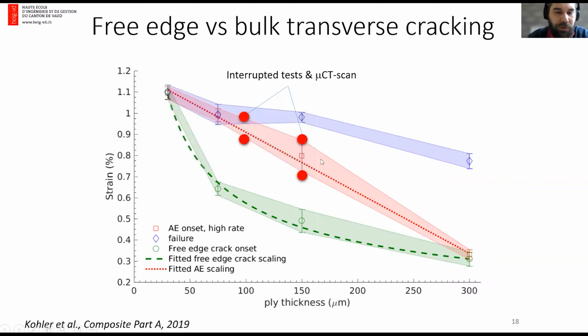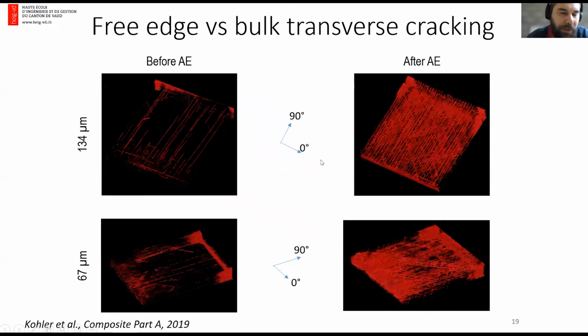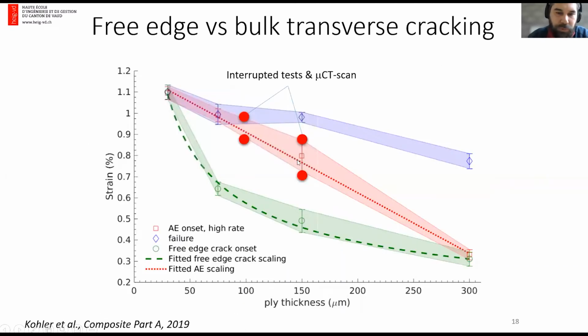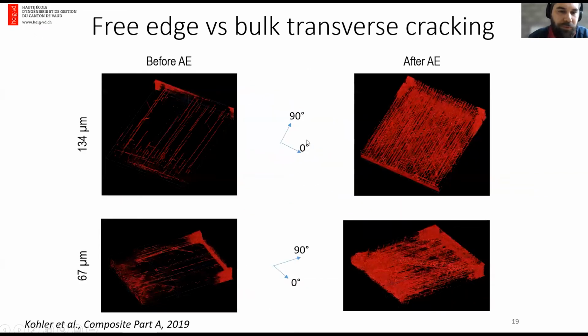To try to understand that, we did some tomography with one observation point right before the onset of acoustic emission and one right after. We can see that before the acoustic emission onset, we have many small damages close to the free edges, but these are very small cracks that appear on the edge but don't propagate in the center, while we have only just a few large transverse cracks here.